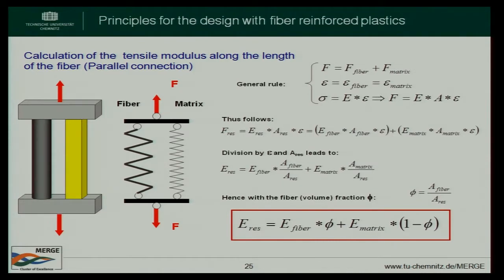Okay. Now, if you apply some force, some load, the stiff spring, the stiff fiber, will take all the load, and the weak matrix will go along. So we have the same elongation, but the sharing of the force is totally different. The stiff fiber will take more or less all of the load, the weak matrix not so much. And therefore your calculation of the total resulting stiffness, the tensile modulus, is related to the tensile modulus of the fiber and to the fiber content.